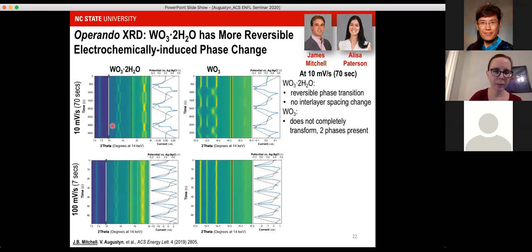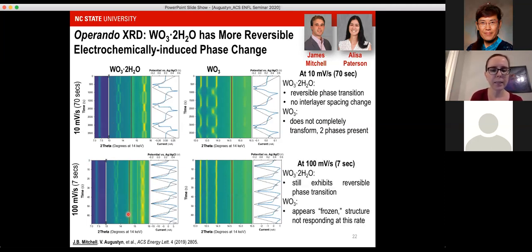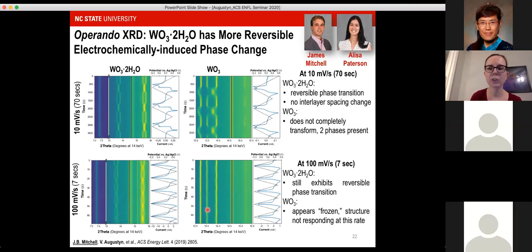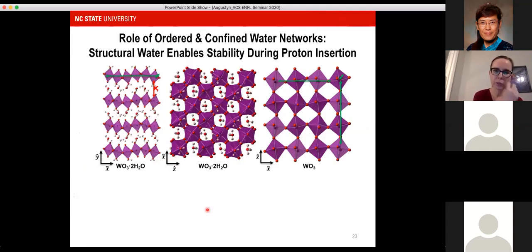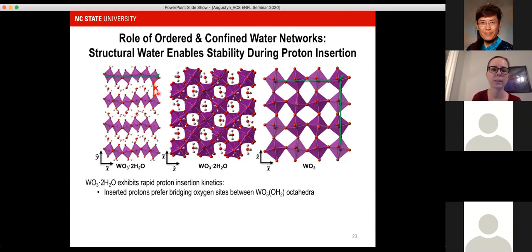If we push our electrodes to go 10 times faster, we see that the hydrous material is still able to keep up, goes through this transition. The time scale of it is much shorter now because we're going at a faster rate, whereas the anhydrous material is essentially frozen. It's stuck, not able to respond at all at these scan rates. So what we found from this story is that these ordered and confined water networks, what they're doing in the materials is that they're providing structural stability during the electrochemical redox process.